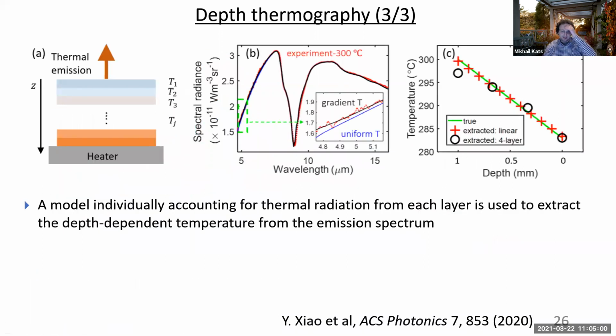And so here is the measurement and also the extraction algorithm. Over here is the spectral radiance measured versus the wavelength for an experiment where the stage that was used to heat up the sample was at 300 degrees Celsius. Even though it might be hard to see, there's actually 3 curves on top of each other over here. I'm zooming into this little region, and you can see the 3 curves. There's a red curve, which is the experiment, and then there's a blue curve and a black curve, and those are 2 theoretical curves. So the red curve is our experiment, and the blue curve is essentially the best fit to that experiment with the knowledge of Planck's law, the emissivity of this fused silica wafer, and essentially fitting the temperature. So essentially trying to find the best temperature that minimizes the difference between the theoretical plot and the experimental curve. And the fit is really good. If you look at them, they're directly on top of each other.